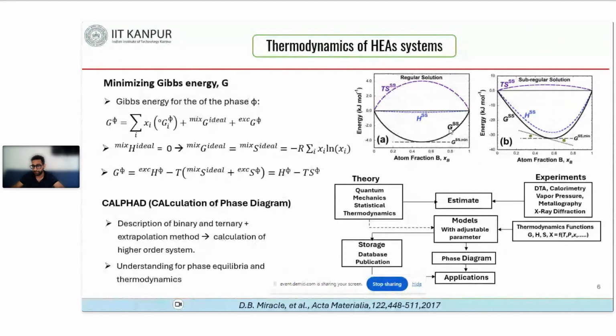But when you go to the sub-regular solution model, although T times S, which is temperature multiplied by the entropy, is symmetric about the equiatomic composition, the enthalpy is not symmetric about the equiatomic position, because when there is ordering or phase separation, the value changes a little bit, and this is dependent upon the alloy composition.